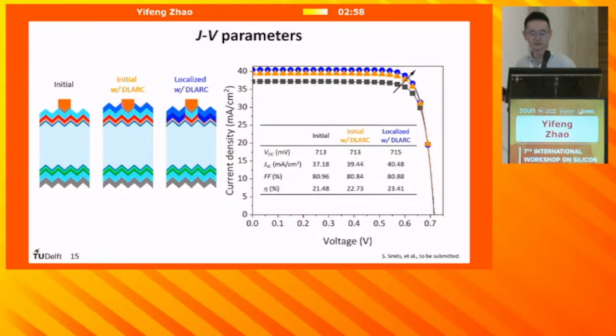But to have a fair comparison, we also introduced this additional cell that has the conventional design but also this dual layer anti-reflection coating, to have a more comparable JSC or reflection loss. With this, we can further see that the JSC is indeed solidly improved by 1 milliampere per square centimeter, without losing any fill factor or VOC. It is worth mentioning that we still have significant room for further JSC enhancement, for instance, by fully localizing front layers, including intrinsic layers and these N-type nanocrystalline silicon oxide layers. We can also improve the rear side by using a high mobility TCO and the rear reflector, as we introduced before.